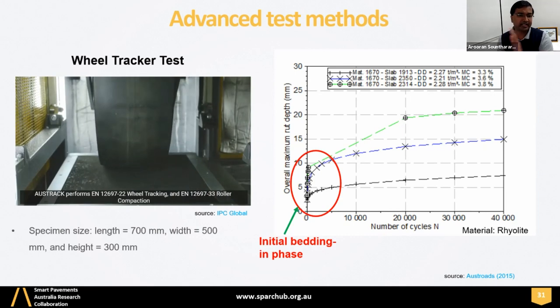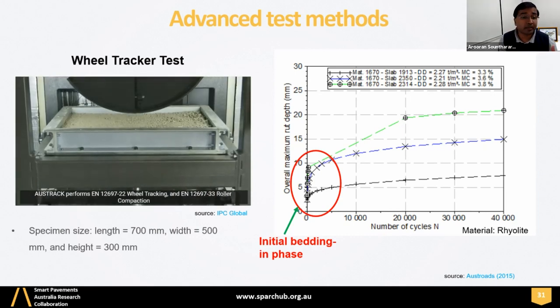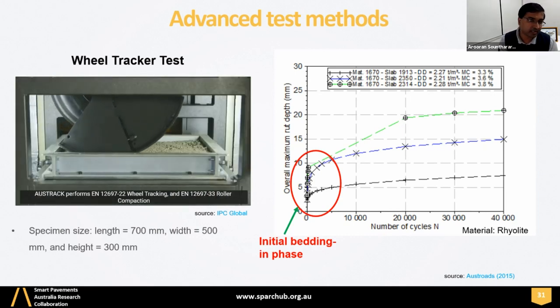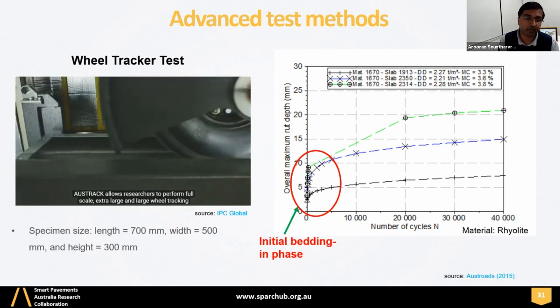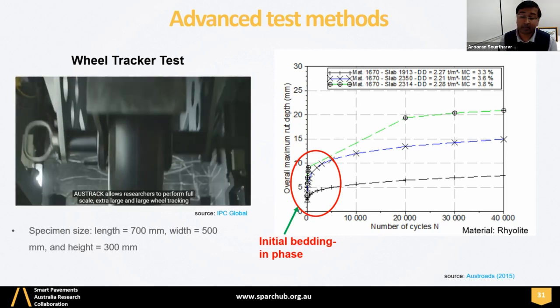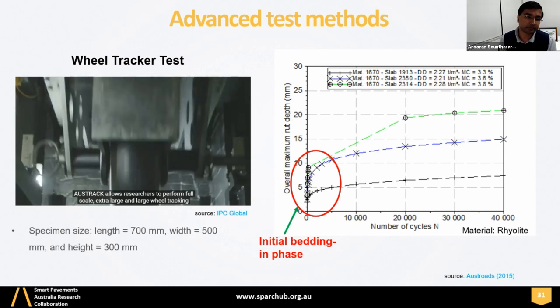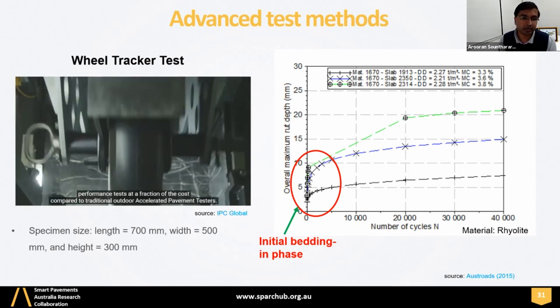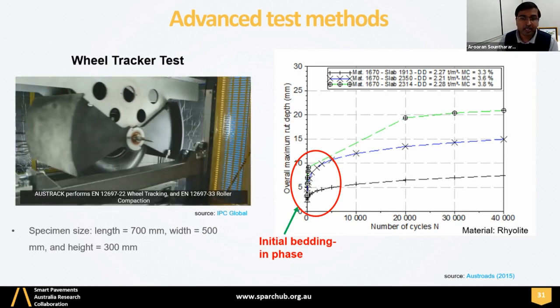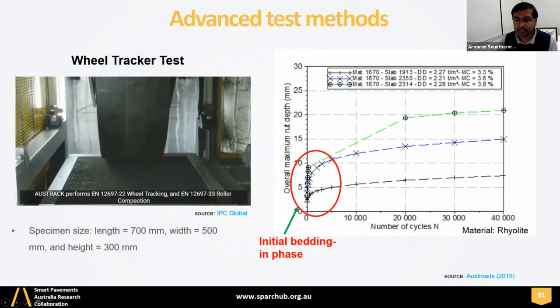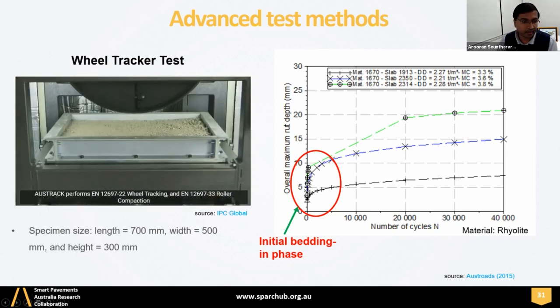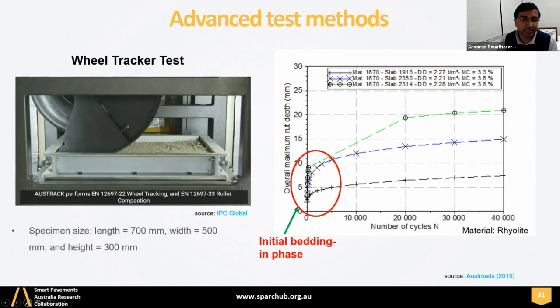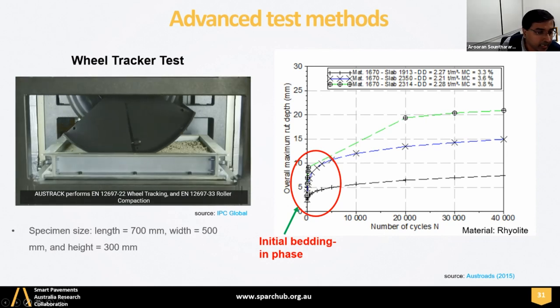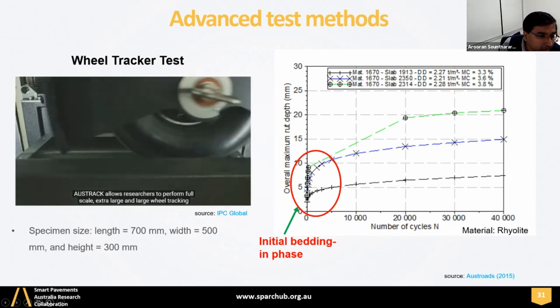So trafficking speed is about 3 to 10 kilometer per hour. That is one of the limitations because it's not replicating what happens in the field, but it replicates the load conditions there in a close way, right? So rutting profile is extracted from Austroads (2015) on your left side. So what you see in the left side is, let me get the browse pen.